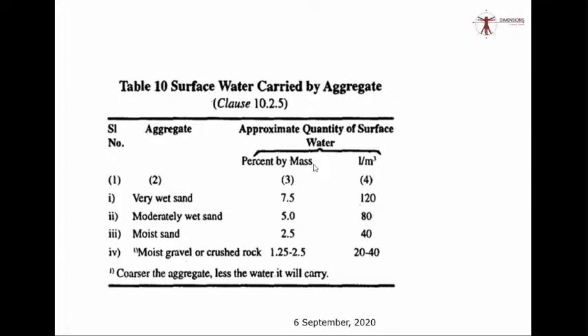Then you can do the same exercise for moderately wet sand by adding 5% to absolutely dry sand. Moist sand, you can do it with 2.5%. You can have all the 3 samples in front of you, and by repeating this multiple number of times, you will be able to judge it. And this has to be there if you have to avoid the usage of an infrared moisture meter or the microwave oven at your site. So this will come only through experience, or you have to bypass this and resort to scientific methods in which you will find the percentage moisture content.